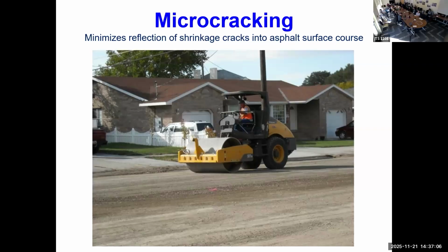of our interstates. Now, some of us might say, wow, that's like putting a mirror on a bed, maybe a stiff bed, but it's nonetheless a mirror on a bed. And sure enough, within 4 years, the asphalt was completely cracked. It was just too stiff. It was no longer really a flexible pavement as it should have been, and it was too thin. And so we had to rebuild that. The reclaimer came in to try to pulverize the cement treated base, and they had some difficulty. In some cases, some of the teeth on the reclaimer drum sheared off.